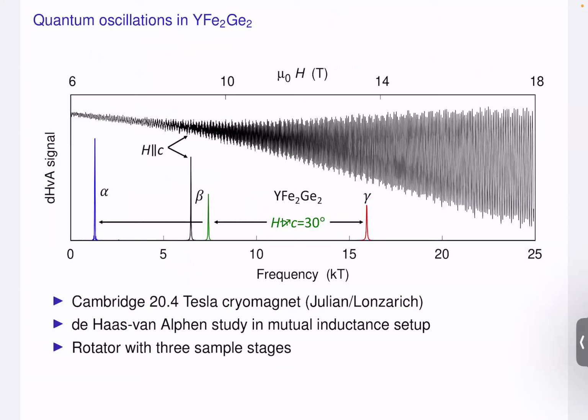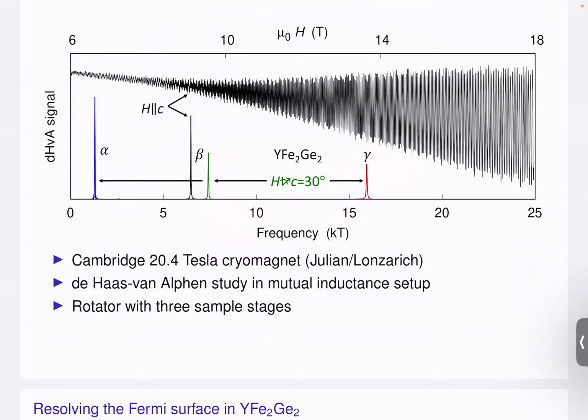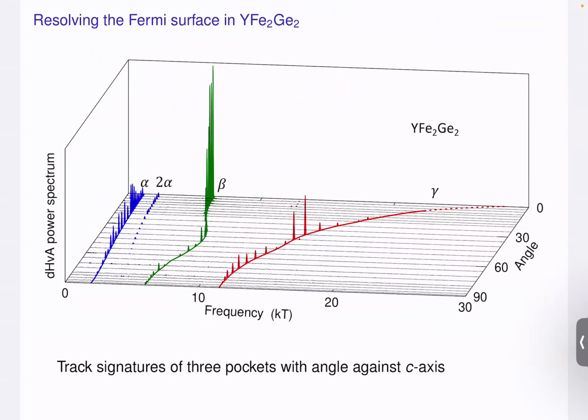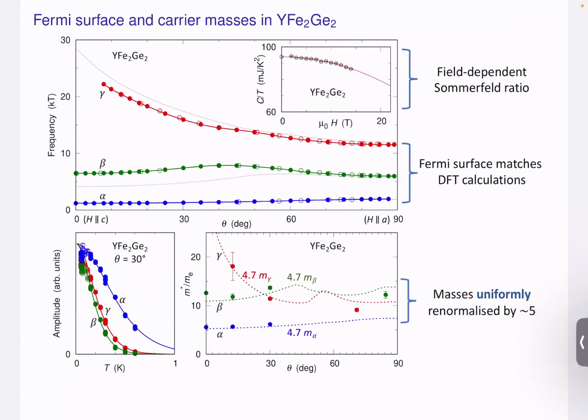Again, this was done in the Cambridge cryomagnet, beautiful quantum oscillations using a mutual inductance setup, dHvA. I don't want to get too much into the technique, but there's a beautiful rotator system there. So you can take the samples, see how the oscillation peaks, the power spectrum, change with rotation angle, and you can track three frequencies here, and they could be assigned to the alpha, beta, and gamma surfaces, three of the four surfaces. The fourth one we only picked out by doing measurements in Nijmegen.